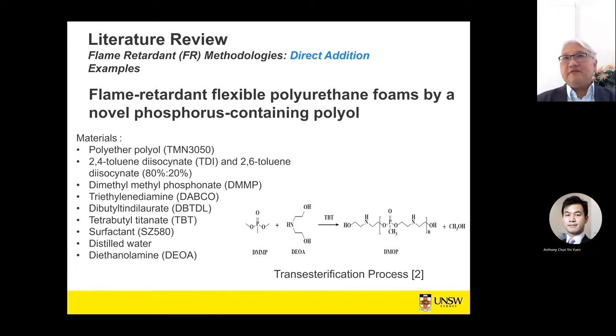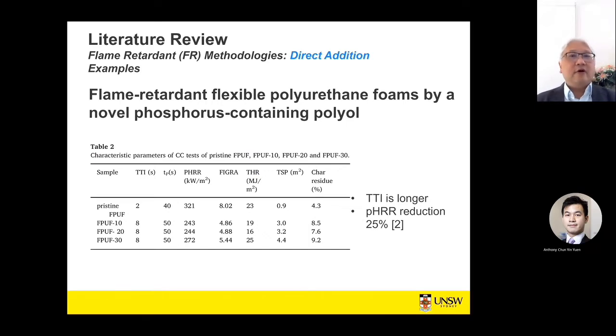One of the ways is infusing phosphorus-containing polyol, a chemical compound which is very rich in phosphorus, into the polymer matrix. Some of the materials that have been infused with the polyol through the transesterification process are listed in the slide here. So the question is, how is the performance with the introduction of this phosphorus-containing polyol? As you can see, without the polyol itself, the peak heat release rate is 321. But with the addition of more and more phosphorus-containing polyol, the heat release rate reduces, quite marginally, to 243, 244, and 272.